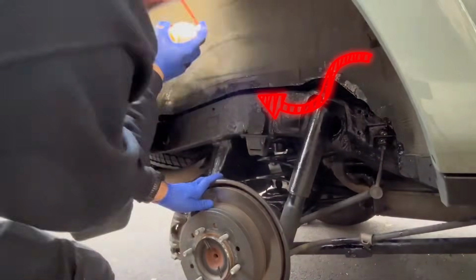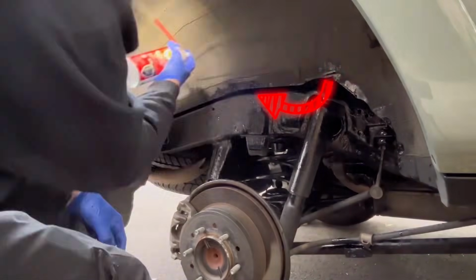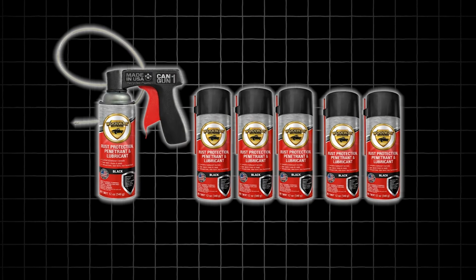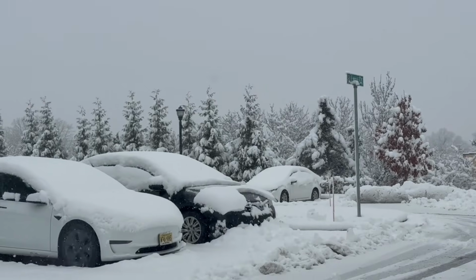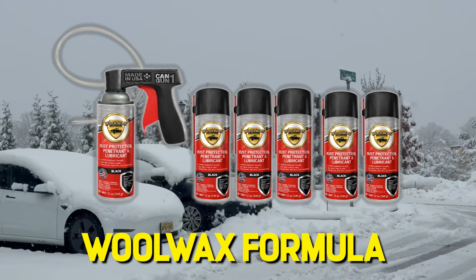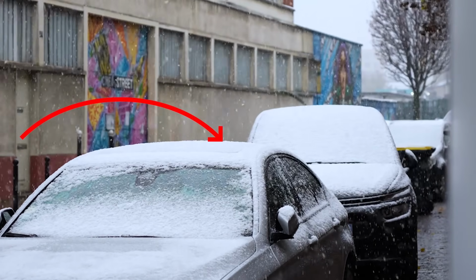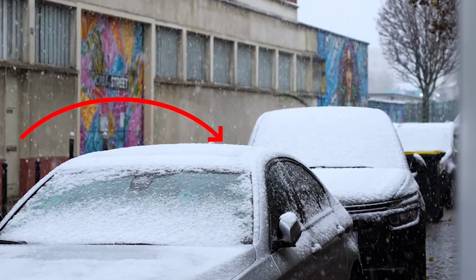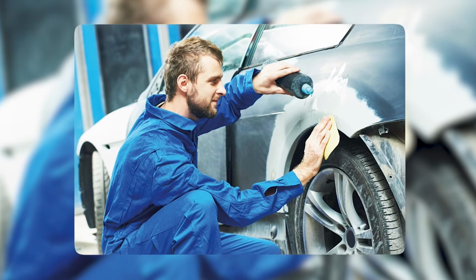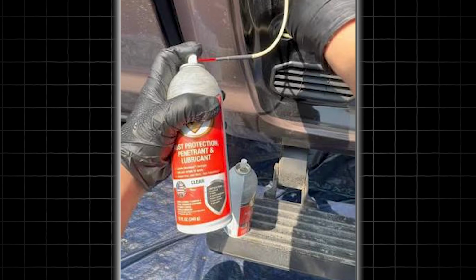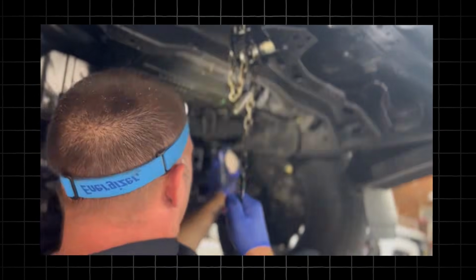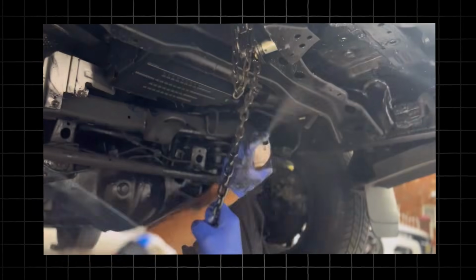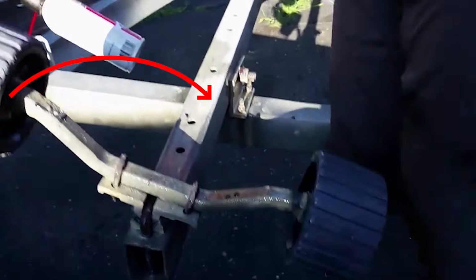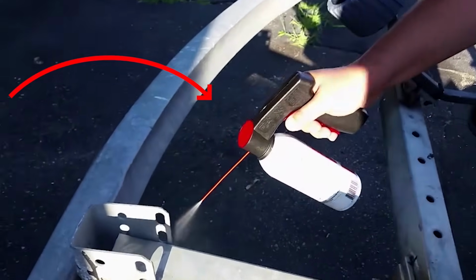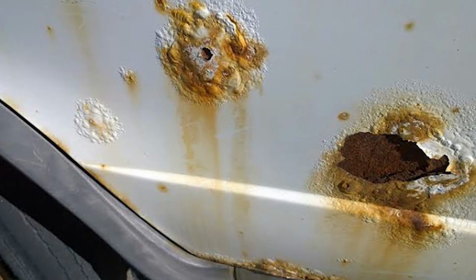The problem is what happens to the flowing behavior in deep winter temperatures, in the climates where undercoating protection matters most. Below -15 degrees Fahrenheit, the Woolwax formula thickens dramatically. At these temperatures, the self-healing flow stops entirely. More critically, the thickened formula becomes brittle enough that road debris impact chips the coating. Rather than deflecting off a flexible film, stones and gravel punch through it. Each chip exposes bare metal to the most aggressive road salt conditions of the winter season. The lanolin formula at these temperatures cannot flow to cover the exposed area quickly enough to prevent initial rust formation.